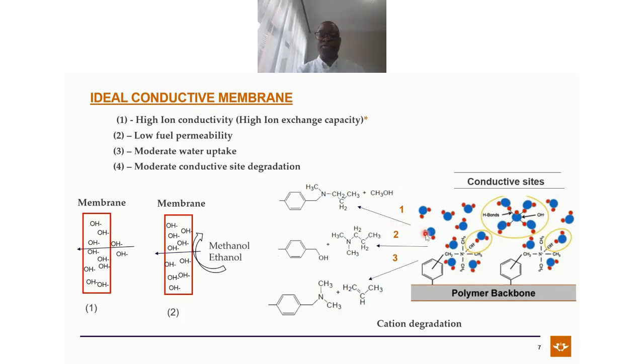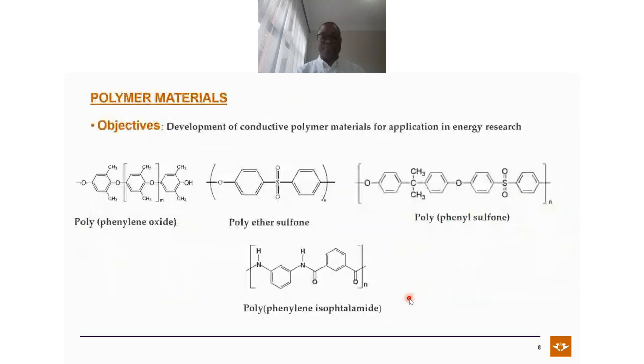So what products are normally produced? If you have OH, you end up having these products: a nitrogen-based component with methanol separation. Once your membrane degrades in this way, it's no longer effective. You cannot use it. You need to change it. Another method which hinders the membrane is the production of OH-based aromatic with amine-based product and so forth. So all of this is SN1, E1, and Hofmann elimination. If you remember those types of degradation, there's nothing we can change with that. We just need to find a way of reducing the speed of this degradation.